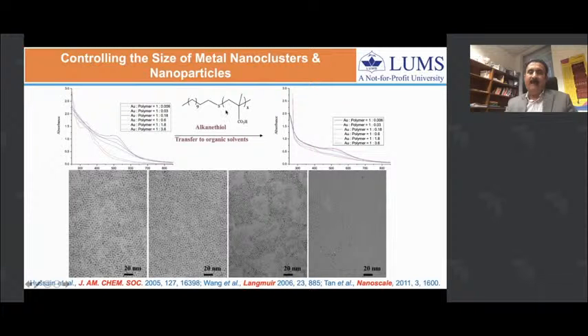By controlling the ratio of this polymer to gold in aqueous media, we were able to control the size of these nanoparticles from 1, 2, 3, or 4 nanometers in just one step method.